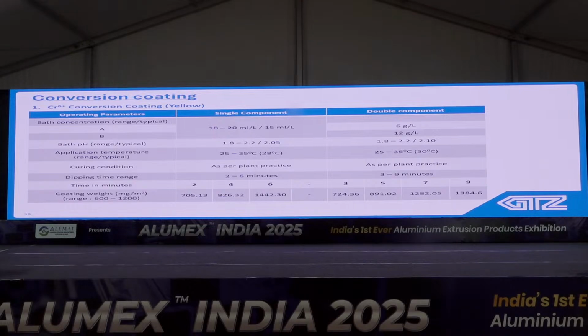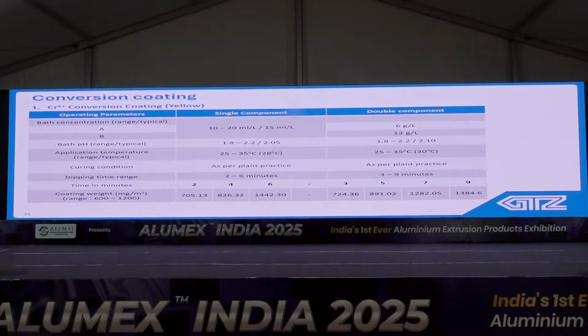And we have done different coating weights at different dipping times, which for single component is 2 to 6 minutes, and coating weight is matching with our normal specification of 600 to 1200. And similarly for double component, dipping time is 3 to 9 minutes, and as time increases, coating also increases, but it is within the specification range.